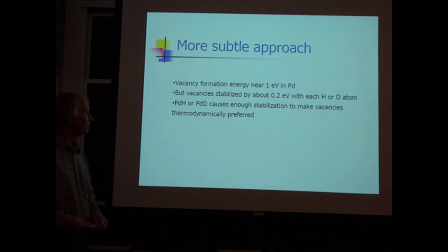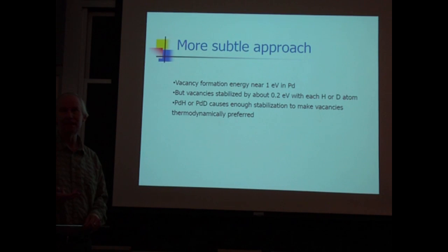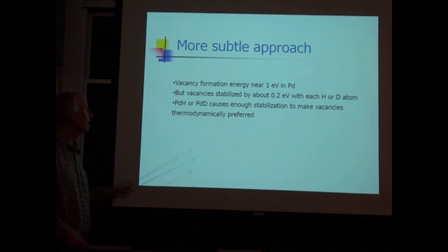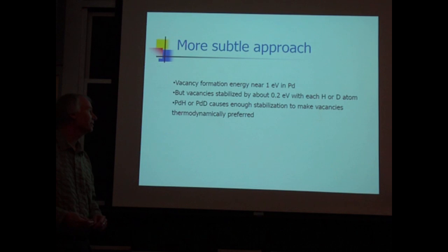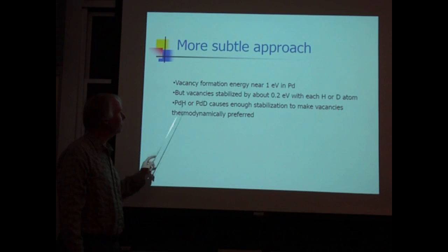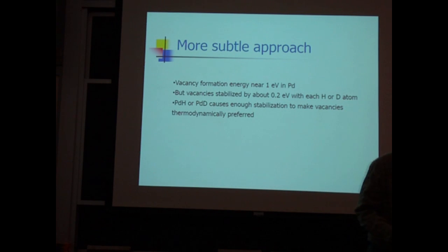There's a more subtle approach. The more subtle approach is to notice that vacancies are stabilized with the addition of hydrogen or deuterium to the lattice. The reason that there are so few vacancies in the first place is that it takes energy to make a vacancy, and it takes a lot of energy. It's on the order of an electron volt. You stabilize vacancies by roughly 0.2 electron volts. The 1 electron volt might be a little bit more than 1 electron volt, but 0.2 might be a little bit less. So by the time you get 5 or 6 around it, hopefully 6 rather than 5, then you've stabilized enough to basically balance out the 1 electron volt formation energy. So under those conditions, if you get high enough loading, you can stabilize the vacancies, and the vacancy phase version of the system is thermodynamically preferred.